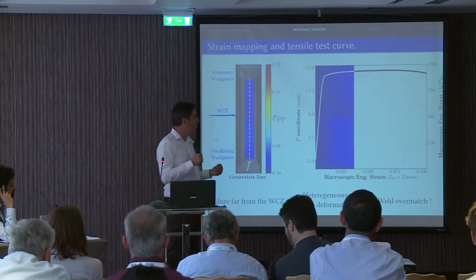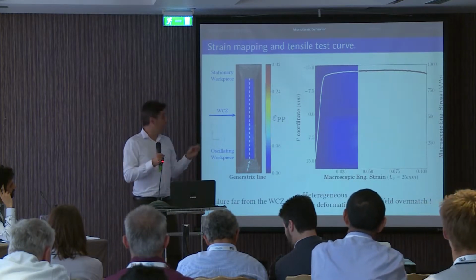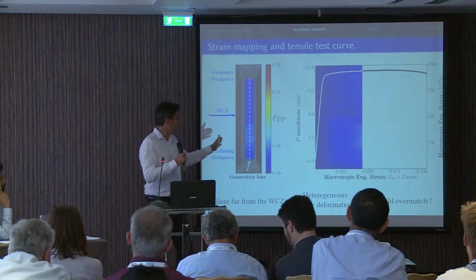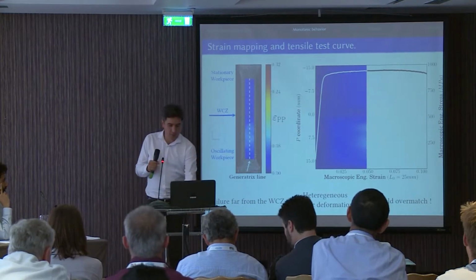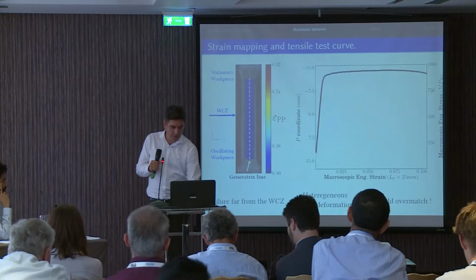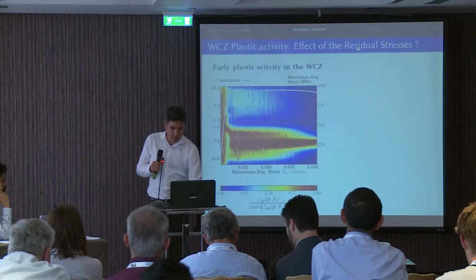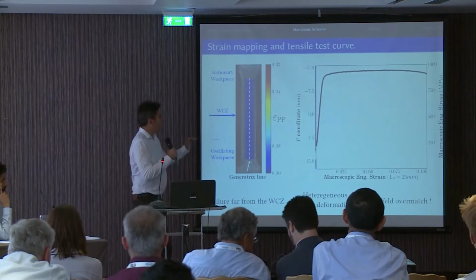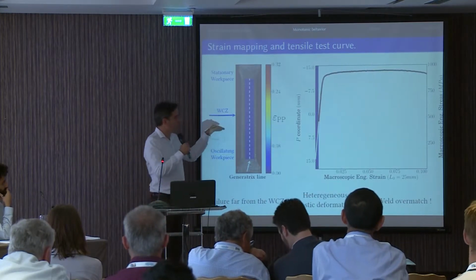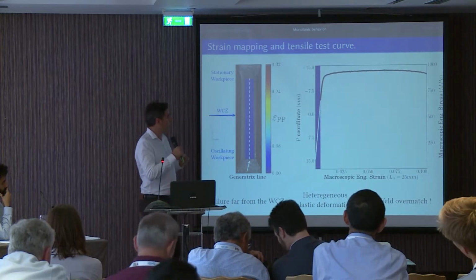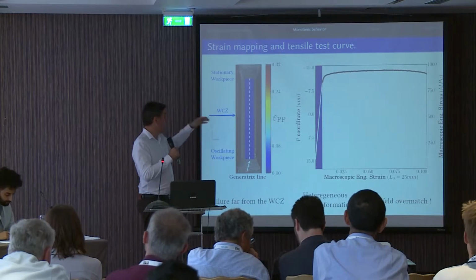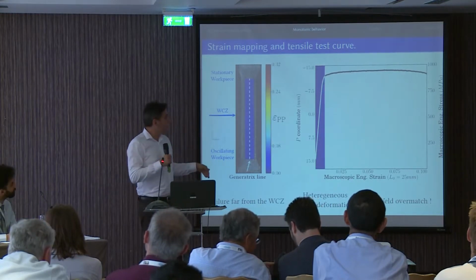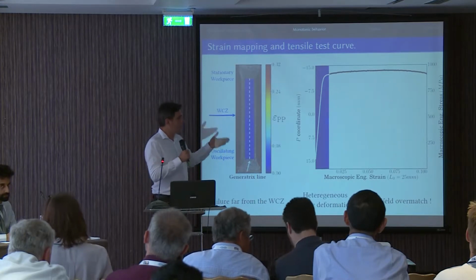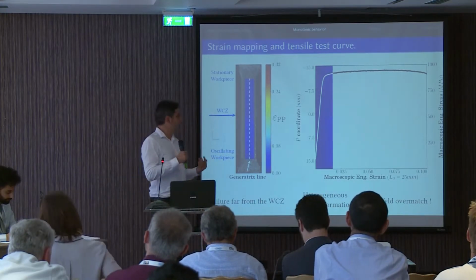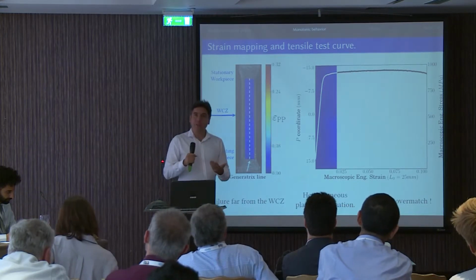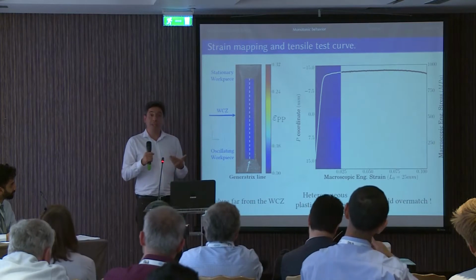This will allow us to study the strain history of this line in a 2D graph. Sorry, this is a little bit slow. With the strain field, we confirm that the failure takes place far away from the weld, and we get to see the plastic deformation, which is very heterogeneous.